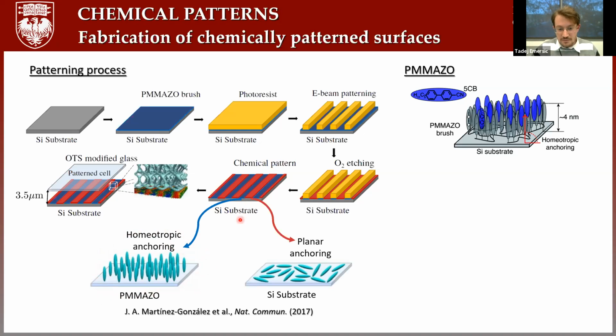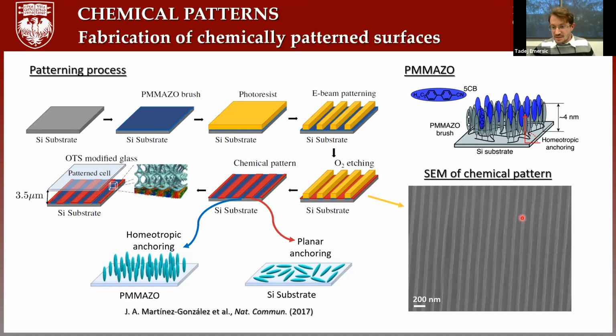And then we have lines where the molecules lay on the surface, right? So planar anchoring. So with this e-beam lithography, nanolithography, we just remove some certain area of the brush, and we create this kind of alternating homeotropic and planar anchoring. On top of that, we put another glass with homeotropic anchoring, and then in between, we inject the blue phase, and if everything is okay, then the system should form the single crystalline structure. This is just an image that shows how the patterns look with a scanning electron microscope.